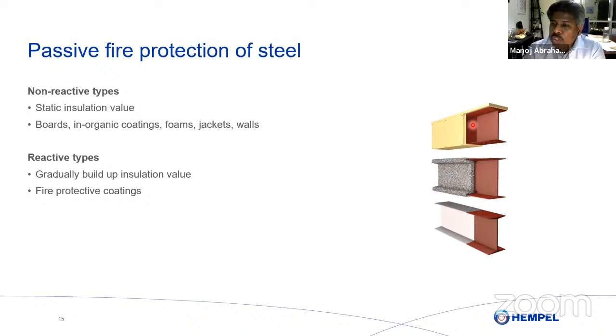But now most of the consultants, most of the end users are asking, will your coating system provide corrosion protection and fire protection? You can see that there are gaps here and you can see corrosion starts here. Similarly here, there is corrosion in the interface between this cementitious material and the steel. So we need to ensure that the system works. After 5 years, or 10 years, you might have a possible fire, and the coating system should be intact to ensure that the system works.